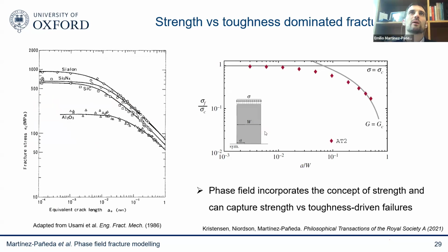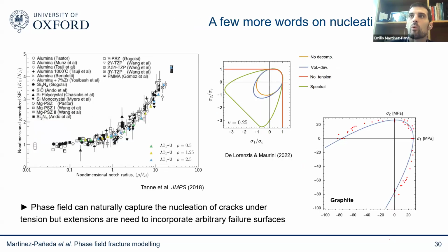And at this point, I'll say a few words about nucleation of cracks in phase field, because this is still an open issue in a way. There's still a lot of people working on this as we speak. And the reason why is that you can show very nicely, and there's this nice paper by Tanné et al., using, for example, notch samples. These are notch samples where they change the notch radius and they compare to experiments on a wide range of materials. So you can show very nicely that the phase field indeed captures the right nucleation strength, is able to calculate very nicely when cracks nucleate, and is able to do so, showing a good agreement with experiments.